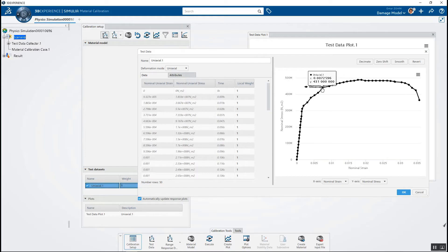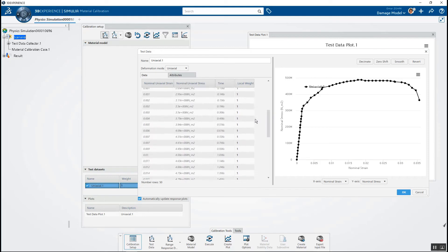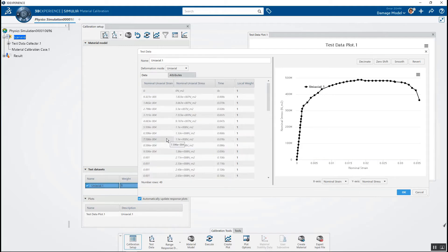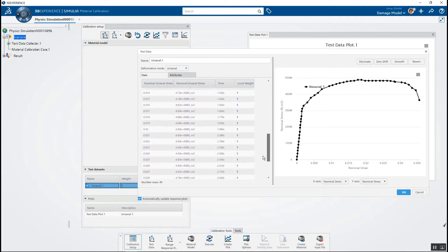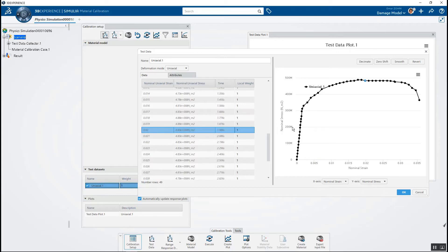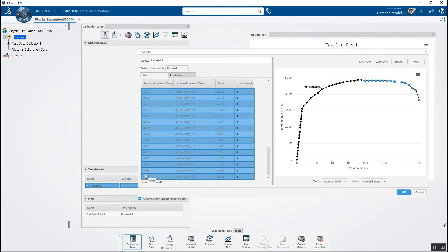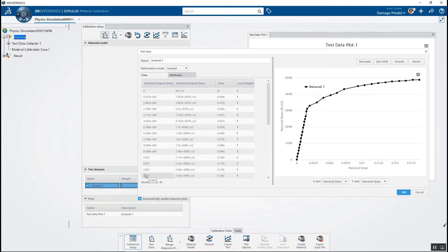You can also see up here I've got two points right on top of each other. I'm going to go ahead and remove one of those points — highlight that one and remove that selection. I could smooth the curve a little bit if I wanted to. I'm also going to get rid of any points above 0.019 strain, since anything above there is above the ultimate stress and we don't want that data. There we go — that's the curve I now want to fit.